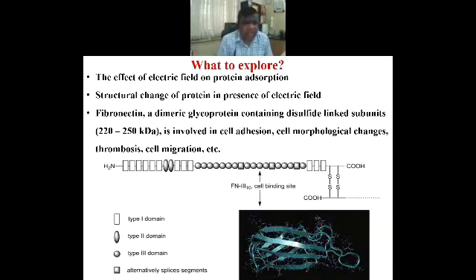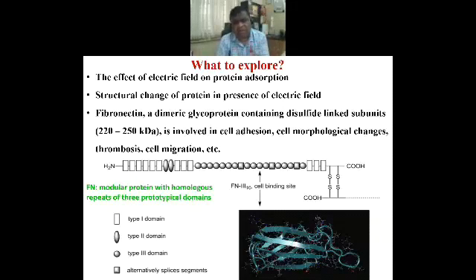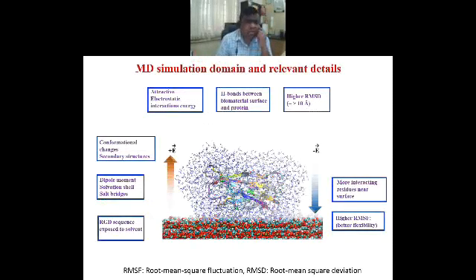So fibronectin has three different types of domains: type 1, type 2, type 3. Fibronectin is essentially a modular protein with homologous repeats of these three domain types, and we have taken the type 3 domain of fibronectin. So this is the molecular dynamics simulation domain. Here you can see the bottom is the hydroxyapatite surface, the 001 surface. It is either strontium-doped or pure hydroxyapatite.